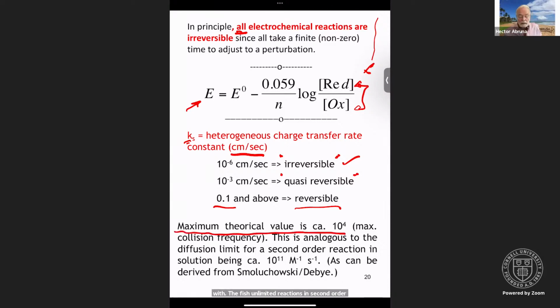This is analogous, for those of you who are more familiar with diffusion limited second order reactions in solution. That's of the order of 10 to the 11th per molar per second, as can be derived from the Smoluchowski expression, meaning a diffusion limited reaction in homogeneous solution has an upper limit of the order of 10 to the 11th per molar per second. The equivalent for Ks in an electrochemical system is of the order of 10 to the fourth, which is blindingly fast. The fastest reliably measured values of Ks are on the order of a few hundred to maybe 1,000. Going to 10,000 is extremely difficult experimentally.